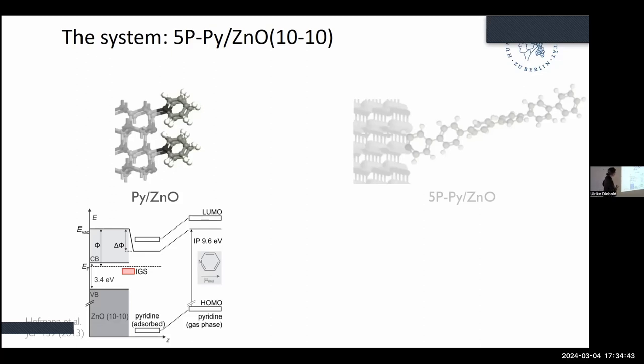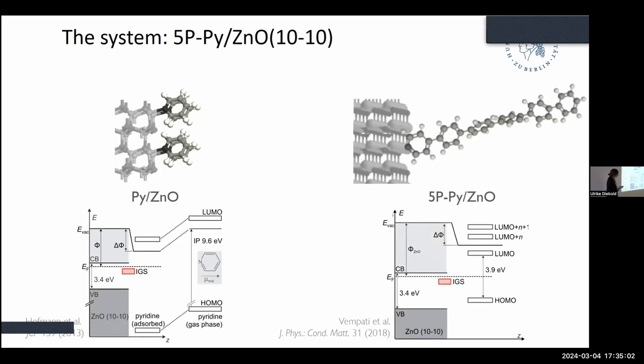So, the reason for this is that you cannot have Fermi level pinning because of the negative electron affinity. Many molecules you put on surfaces have a positive electron affinity, and as soon as you come into the region of the Fermi energy, you cannot reduce the chemical potential any further. Okay, and then 5P pyridine has a smaller band gap, but generally everything stays the same, except for the fact that the electron affinity is now suddenly positive. But you can quite substantially reduce the work function to 2.6 eV still, when you adsorb the 5P pyridine.